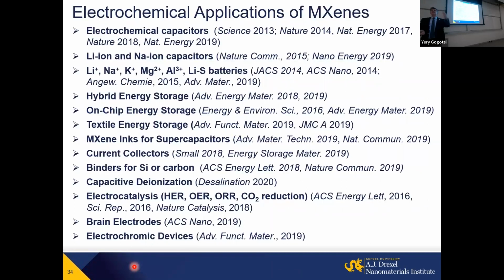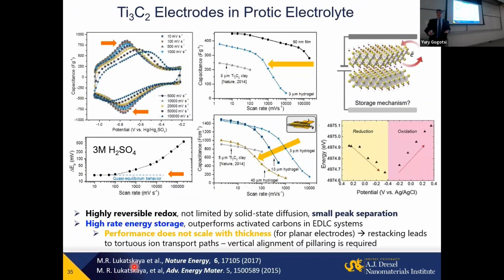But basically, people have been exploring almost every kind of possible battery and supercapacitor application. And we showed that, in fact, what we have been claiming, very fast redox, is possible. If you look at this cyclic voltammogram of MXene in protic electrolyte, sulfuric acid, you will see that close to OCP there is a double layer storage, but there is this wide redox peak overlaid on it. And the separation is about 20 millivolts, so we call it electrochemically reversible reduction. It's basically a symmetric peak.